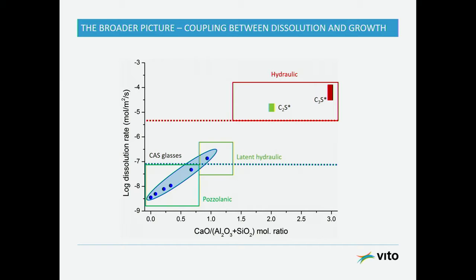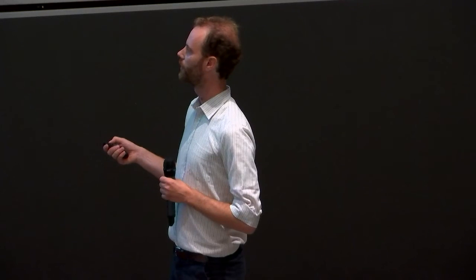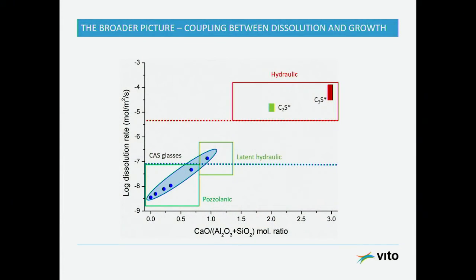So at very low dissolution rates, where we have little calcium, we have typically pozzolanic materials. Then moving up towards higher dissolution rates, we first encounter typically latent hydraulic materials, like this was the slag kind of glass. And then up there we have the hydraulic materials, like C2S and C3S, that have high dissolution rates. And also, of course, they have enough calcium to be able to precipitate hydrates and keep, for instance, aluminum and silicon in the solution lower.